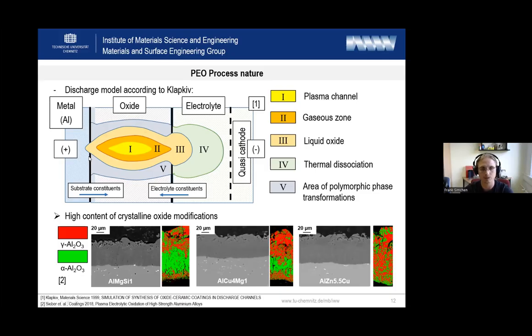And these melting, remelting, and quenching reactions are influenced by practically all process parameters: the electrolyte composition, the applied pulse, and also the substrate. Here we see a nice example of aluminum substrates which were treated by PEO under constant conditions regarding electrolyte and electrical regime. But depending on the chosen substrate alloy, we get a completely different distribution of the appearing oxide modifications. So we have here the conventional crystalline aluminum oxide, and the green phase is corundum, which is a very hard oxide modification.